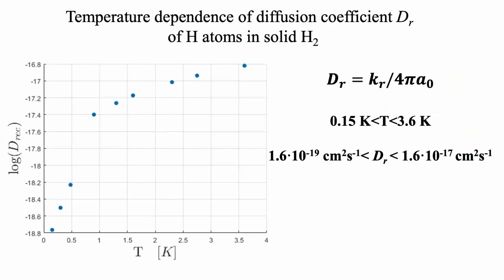How do we calculate the diffusion rate? Because it's a diffusion-limited process, the relation between the recombination rate of hydrogen and the diffusion coefficient is given by this formula, where a0 is the lattice parameter for molecular hydrogen.